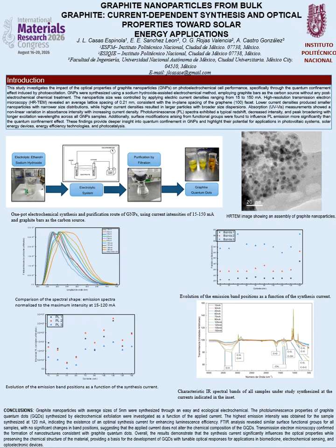It is noteworthy that during the synthesis of the carbon nanoparticle samples, we maintained constant growth and purification conditions to minimize variations in surface oxidation and functional group modifications among the samples, thereby reducing the influence of surface states on PL emission. The GNPs were synthesized by means of an electrochemical approach, using graphite pencil rods as the carbon source and as electrodes in an electrochemical cell. Through careful synthesis and purification, we successfully obtained GNPs using this electrochemical procedure, achieving emission ranging from violet to red,